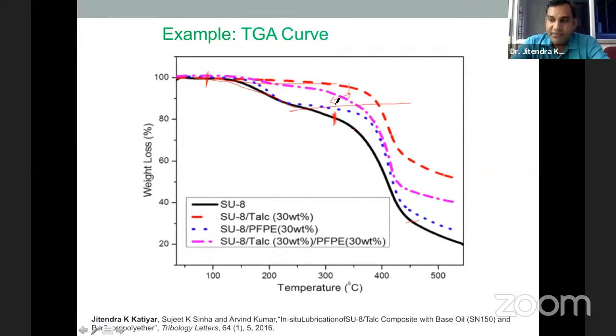After adding the filler, is your polymer behavior changed or not, and is the thermal stability changed or not? Because sometimes the temperature at the interface is always higher than at the outer surface. Wherever two bodies meet each other, frictional heating sometimes generates instability in your coating. If the coating you have developed is not sufficiently temperature sustainable, then it is not suitable for that particular purpose. That is the basic thing in the TGA analysis which we perform.